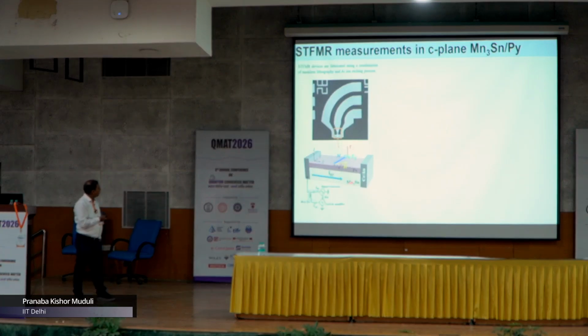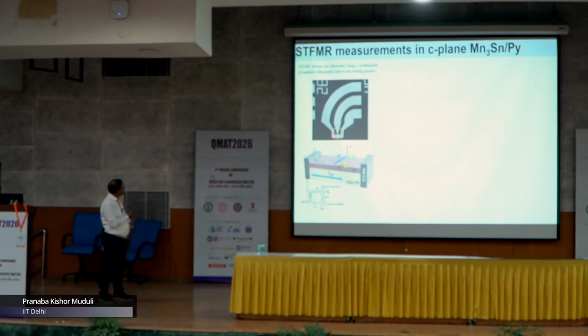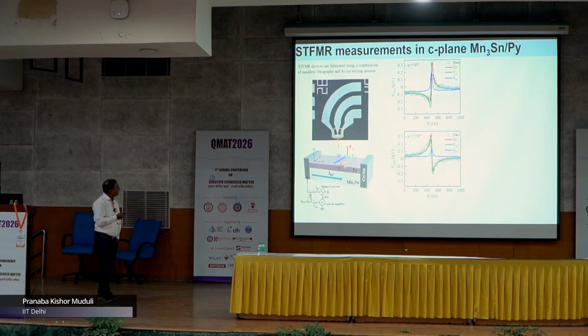We did this by fabricating this kind of devices. We have Mn3Sn and permalloy, and then you have this coplanar waveguide. This is the setup, and we did these ST-FMR measurements. If you look at the example spectra, and look at only the symmetric component, the blue one, as you change from 40 to 220 degrees, that is, basically reversing the magnetic field, the sign of the symmetric component doesn't change. This is a signature that there is a magnetic spin Hall effect present in our sample as well.